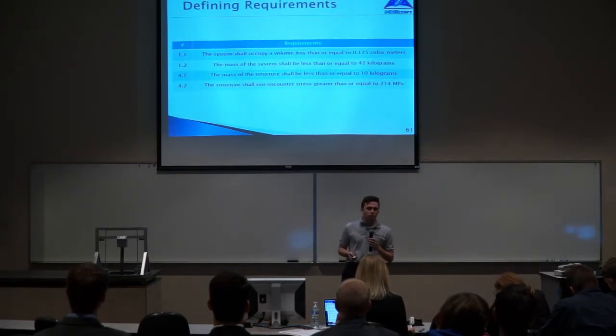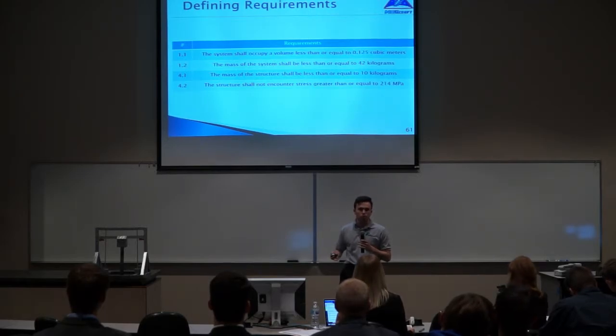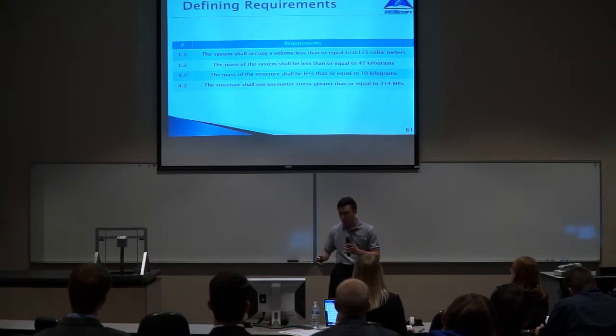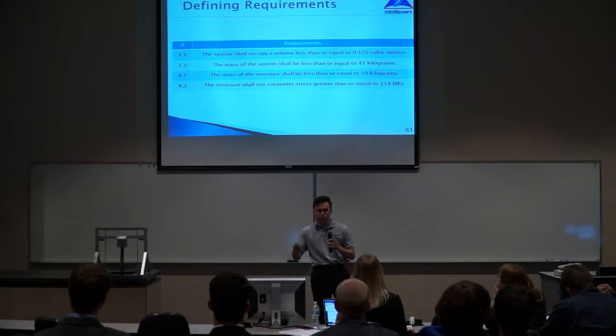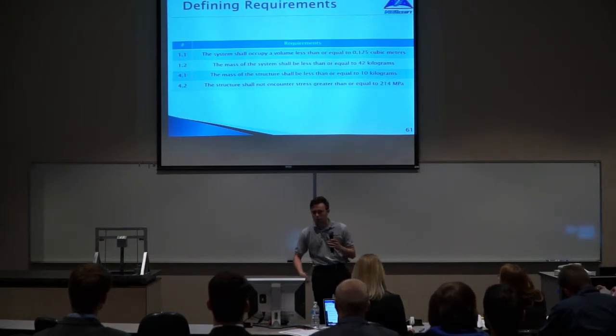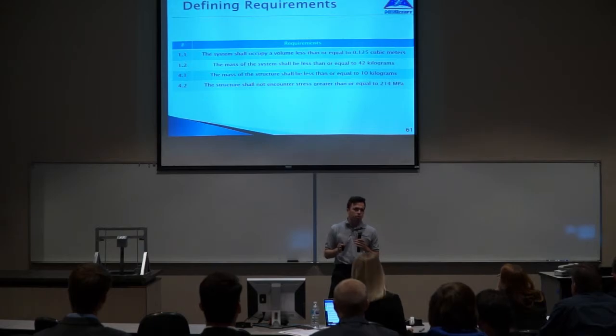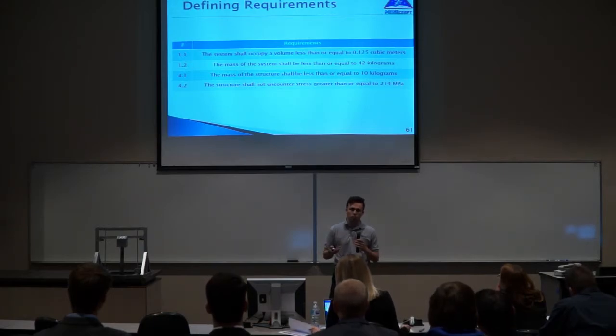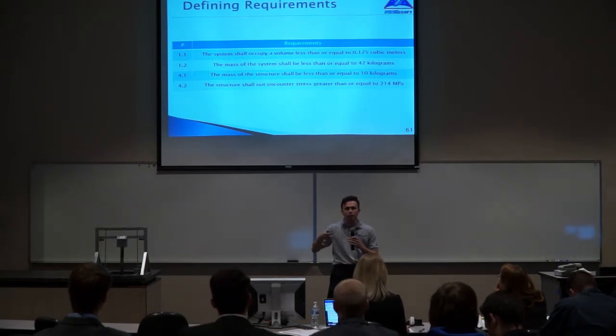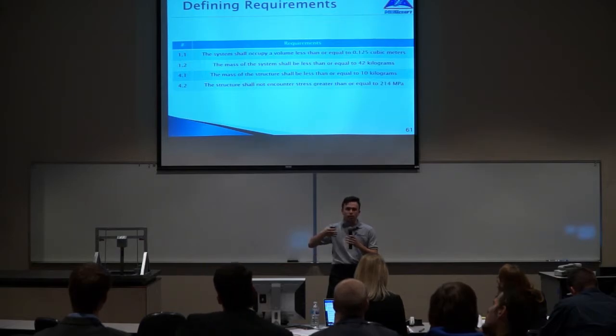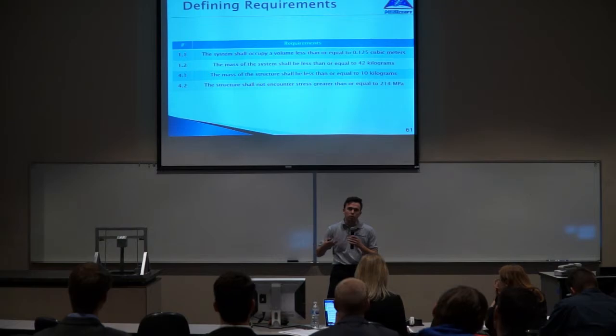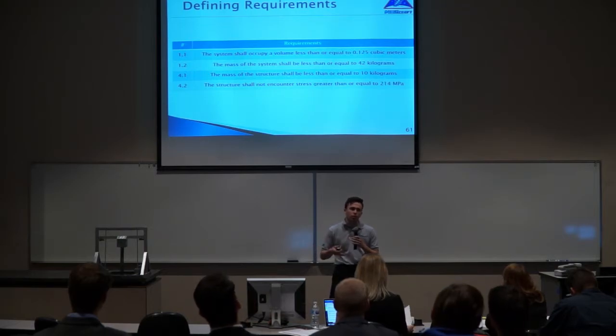The first requirements I had to take into account were the system level requirements. The entire system can be no larger than 42 kilograms, and must fit enclosed within a 0.125 cubic meter, which is a half meter on each side. My subsystem in particular could not exceed 10 kilograms, validated by an assumption of aluminum being used as well as the space it was allowed to inhabit, making space for the other drill components. There was a volume of the drill that was already calculated, and that volume was subtracted from the overall volume, leaving me with a margin of error I was allowed to deal with.